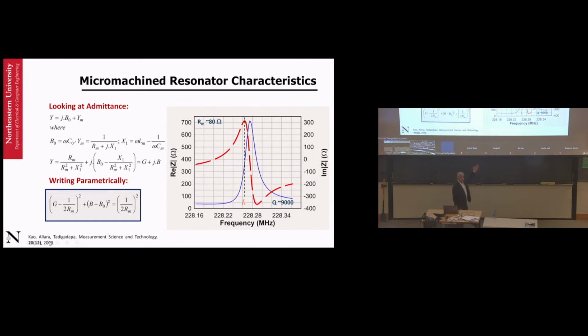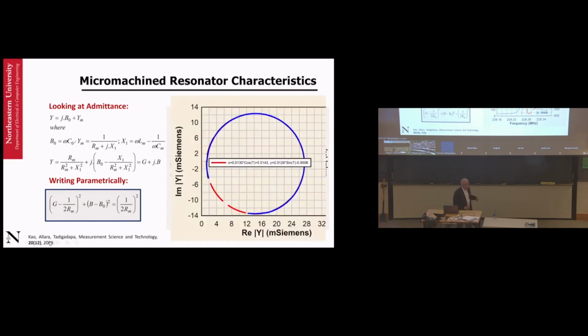Okay, so we also have a very good Q factor. See, the Q factor is no more 52 million. It's only 9,000 now. There is a problem because quartz has an intrinsic limit to how high a Q factor you can get. The f times Q product, the fQ product, is limited to about 10 to the power 13, okay? If you do the multiplication of 228 megahertz with 9,000, we are only an order of magnitude away from that theoretical limit of quartz. This is on a device, and that is the theoretical limit of quartz. So the device has its own losses beyond what the material has. So therefore, you can see that we are starting to manufacture devices that are pretty close to very good performance.